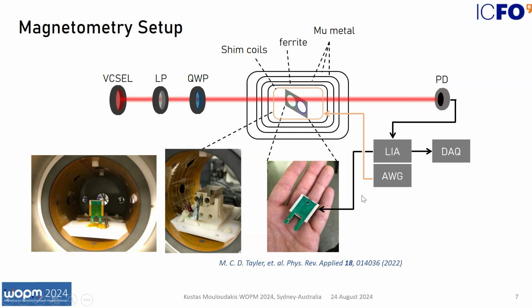We sandwich the vapor cell between these two biplanar coils, these green PCBs that I'm going to talk about in a minute, and everything is placed in this casing with a thin layer of aerogel for insulation. And then this sensor module is placed in the magnetic shield. We use 3 layers of mu-metal and a layer of ferrite. The residual field in the shield is about tenths of nanotesla, but then we use the coils to reduce it even further to the order of 1 nanotesla.